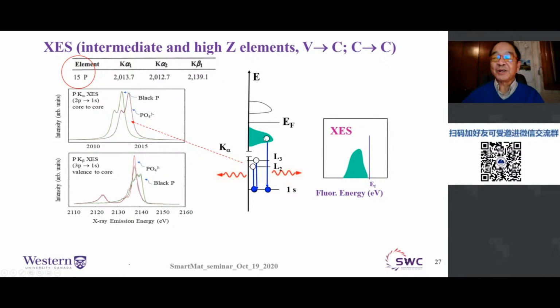But if you do the valence-to-core transition, then we get the so-called K beta in this case, and we can see a very different spectrum. The reason being the valence band of black phosphorus is very different, because it is a broad band, whereas the phosphate is a more narrow band, right? So this is a very powerful technique to understand the chemical shift as well as the charge distribution.